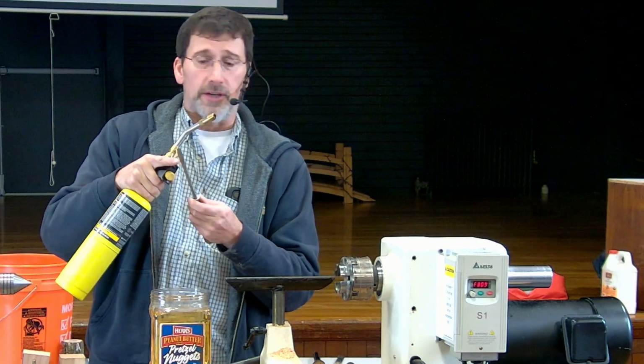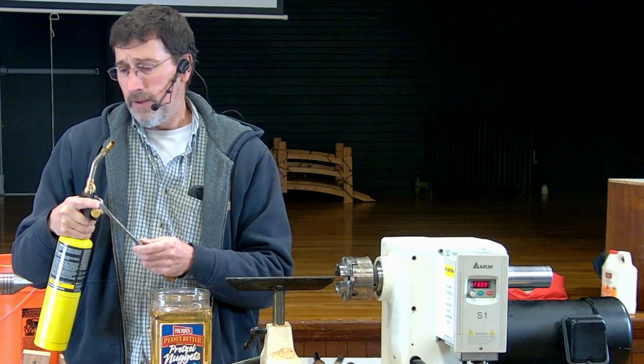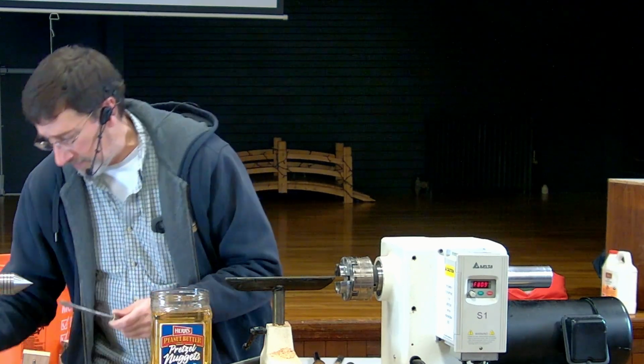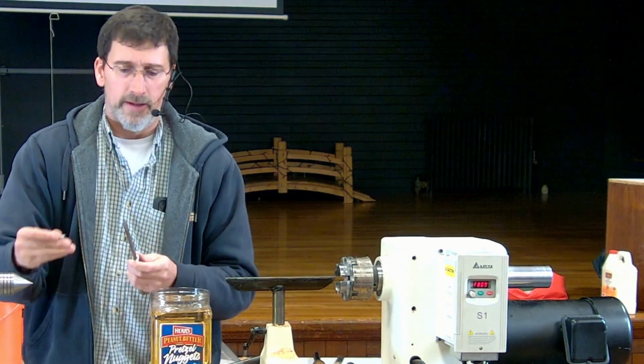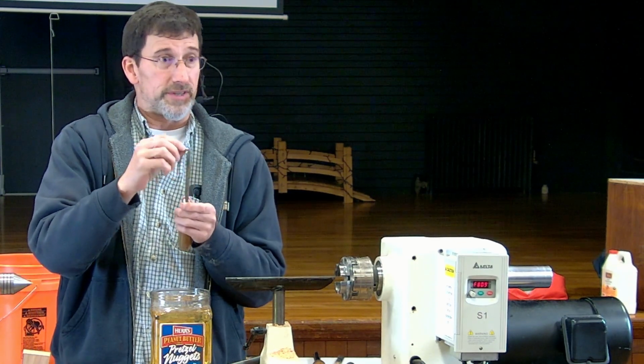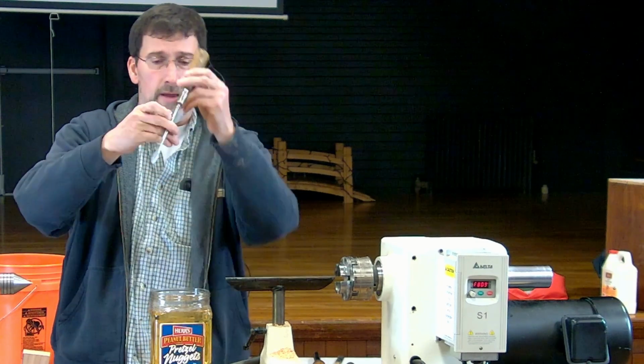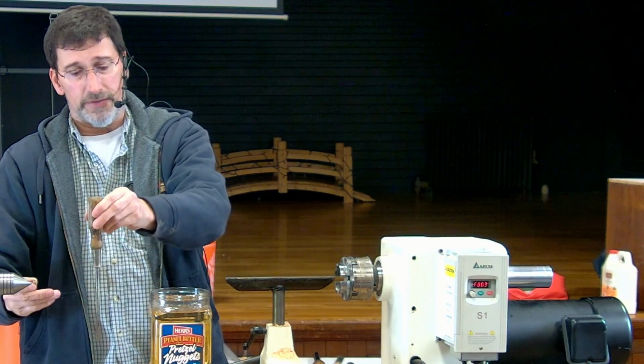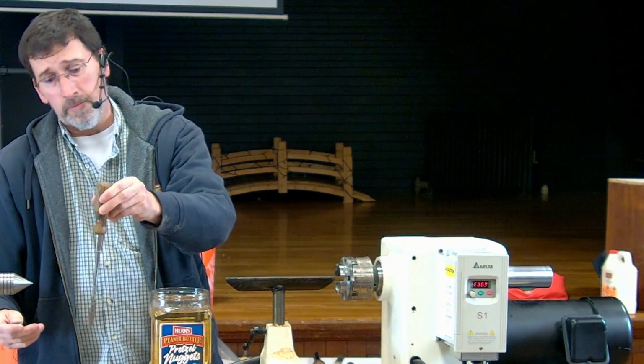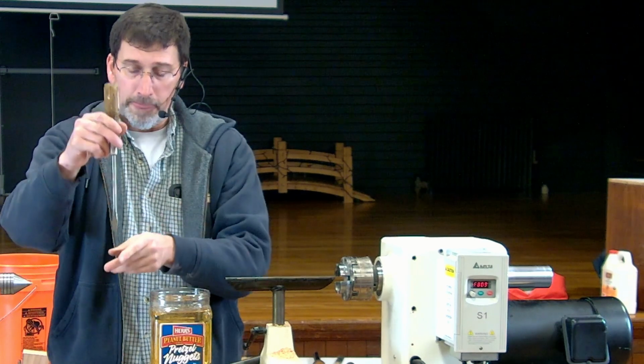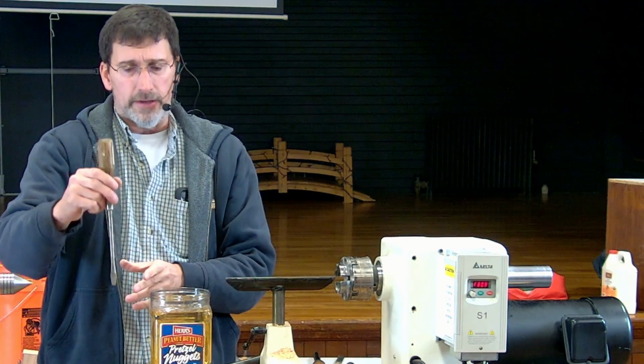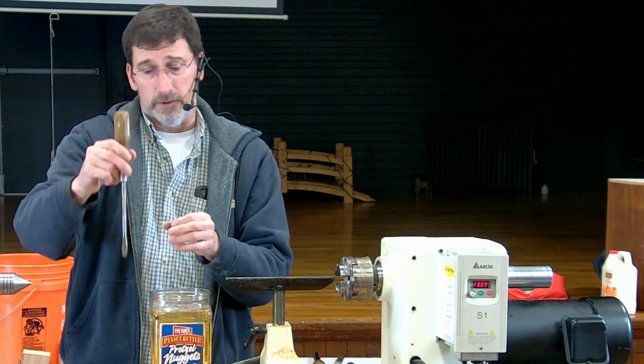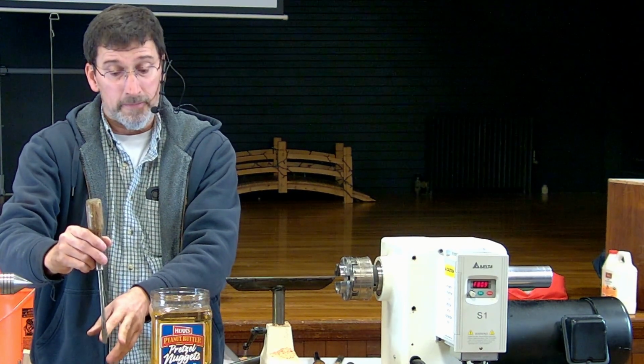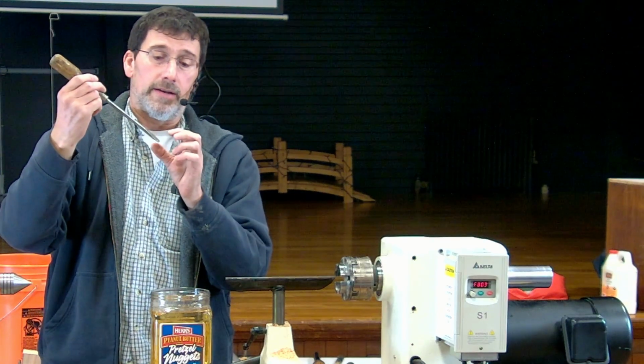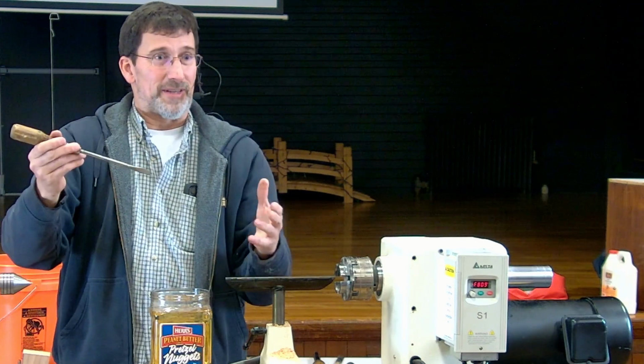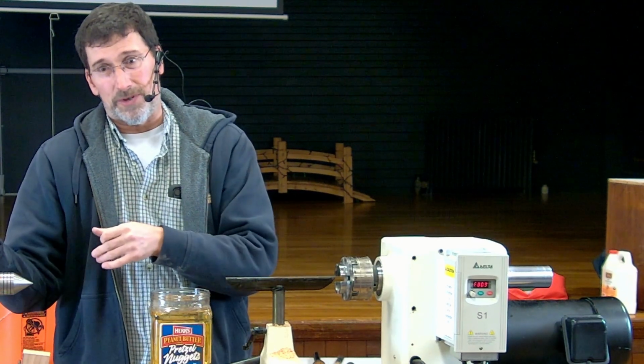And you'll see it start to change color. When it starts to glow red, go a little bit further. And when the magnet no longer sticks, you're at the right temperature. Plunge it straight in. You can lift it up a little bit, move it down. Now, if you're really good, you dip it in and you lift it out before it completely cools. So when it gets to about 500 degrees, you lift it up, and that will temper it at the same time, and you don't have to do the separate tempering step.